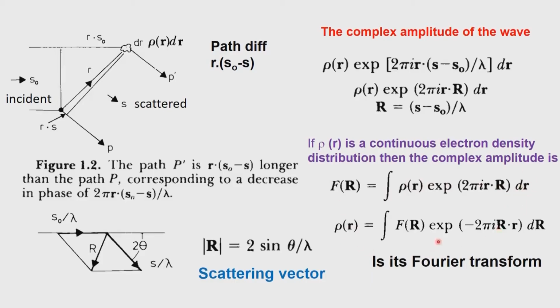We keep on repeating until the rho of R which is measured and the rho of R which is calculated eventually go towards 0. They may not go exactly to 0, but they go towards 0, and then we say we have determined the structure accurately. So, please remember that these two equations, which are Fourier transforms of each other, are actually lifelines during the structure determination protocol.